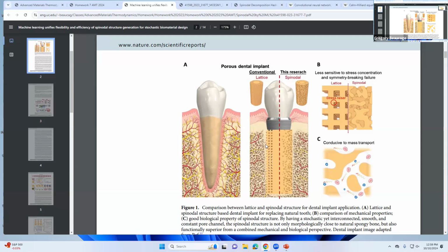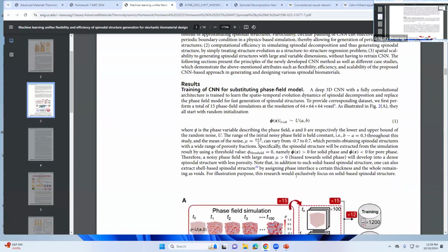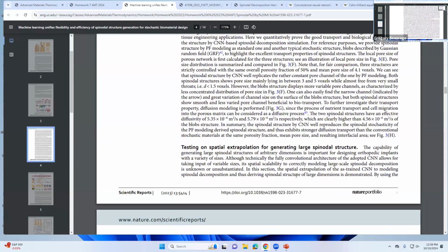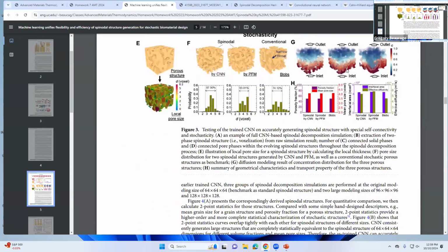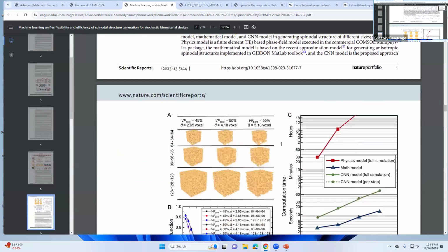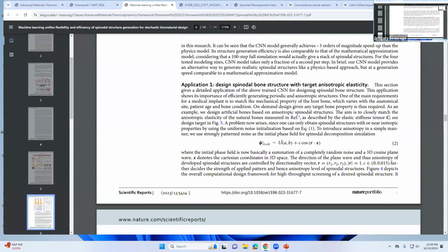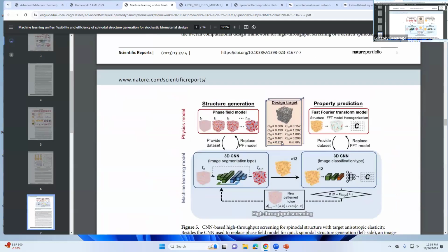He does do something. Once you have all the voxels set up where the material is, and you can make a large scale piece of this thing, then in a computer simulation you can do the flow measurement. So you can do that transport measurement through it. You can measure the diffusion through it like he's showing. But you can also take that structure and pull it and do an Instron stress strain curve on it in 3D. Okay. So then when you do that, you get the 3D moduli of the thing.